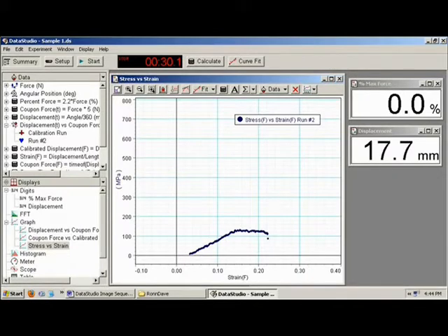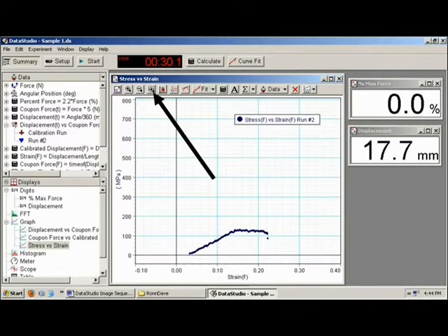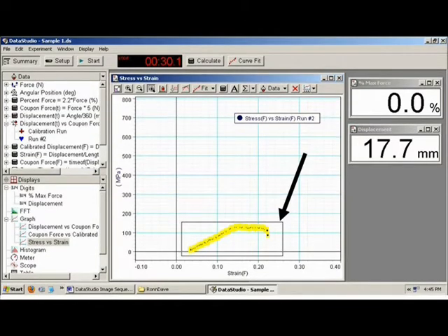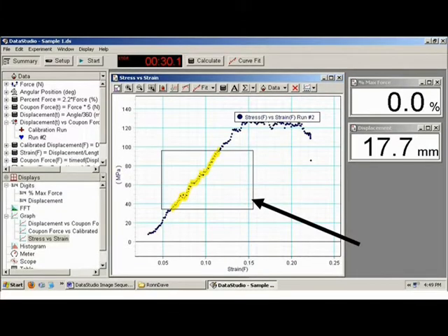To analyze your data, use the Zoom Select tool to zoom in on your graph. Simply click and drag to draw a box around your graph. To find the modulus, click and drag with the cursor to place a box around the linear portion of the graph. Ensure that you do not include any rough part near the beginning of the graph, and ensure that your selected data stops short of the yield point.